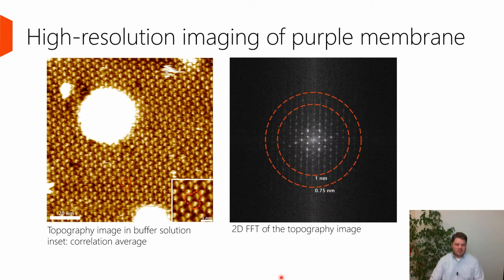And what you see is you have these 2 circles at 1 and 0.75 nanometers, and there are some spots that are outside of this 0.75 nanometer ring, which means that the resolution is actually higher than that, and this is a really good resolution on this kind of sample. And I want to remind you, this was taken with a 100 by 100 micrometer XY range scanner.